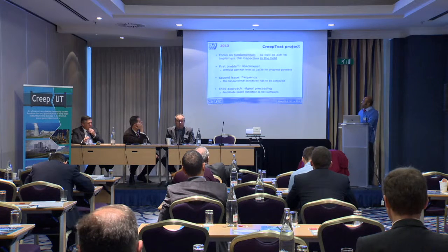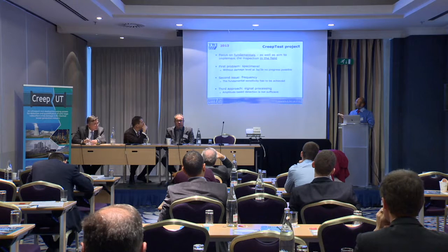So the first problem we faced was specimens. Up until that point, we had been receiving specimens from power plants, things that had been in service, which the power plants obviously were rightly concerned about for creep damage, but there was no obvious evidence of actual type 4 damage. Now, it would have been possible to search for this type 4 damage, and the only way to really do it is to section it. But of course, once you section it, you destroy the specimen at the same time. So it was not really an approach that was going to be viable. First of all, to section these components, like the ones you saw earlier from the header, takes a lot of money. And even after that, it's no guarantee that you will actually get any subsurface damage, which you can then use to do your work on. And so we had to create specimens.